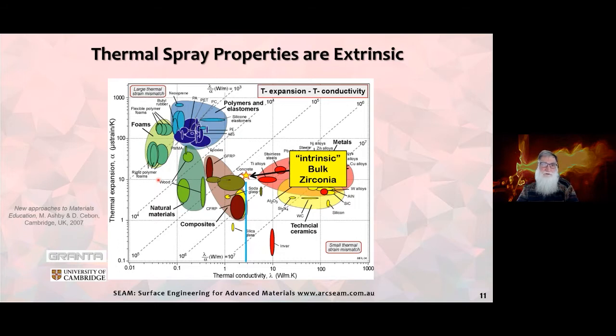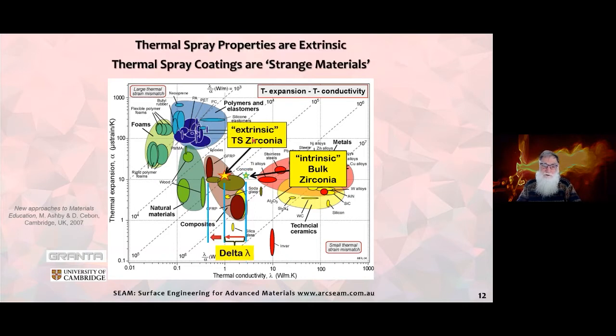So many of you will be familiar with the so-called Ashby maps, but what we've got here is we're plotting the thermal expansion on a logarithmic scale with regards to the thermal conductivity. And here is the material of interest. This is bulk zirconia. So bulk zirconia has a thermal conductivity of about 2 to 3 watts per meter Kelvin. Keep this point in mind, because now if we produce this coating by thermal spray, the watts per meter Kelvin is halved. By conventional thermal spray technology, it is halved to 1 watt per meter Kelvin. The thermal expansion stays the same. And you say, so what? What does this really matter?